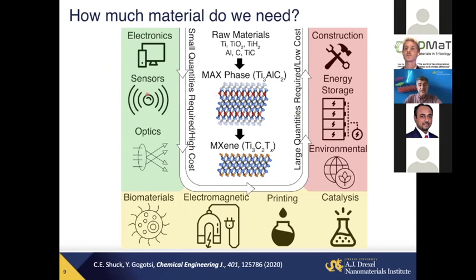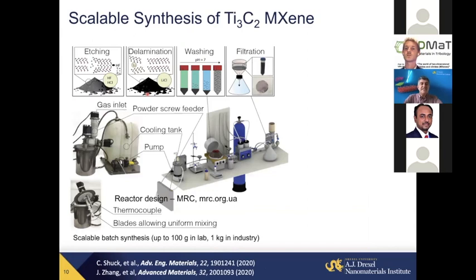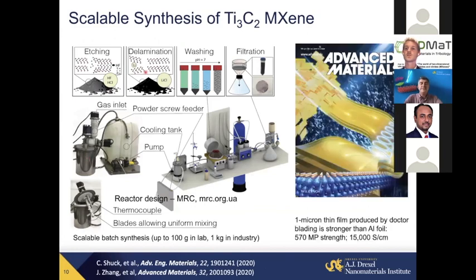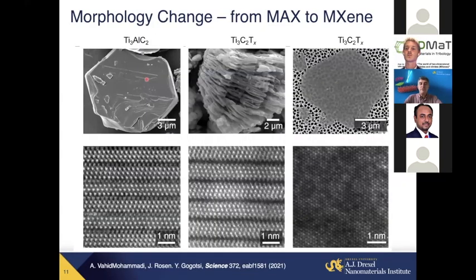MXene, all these materials can be made in a scalable way because we take a ceramic powder, we put it in a reactor, we etch it, we produce MXene, which can be after that processed into films, layers, whichever way you make here. So this is how we start. We start with this ceramic powder, MAX phases.